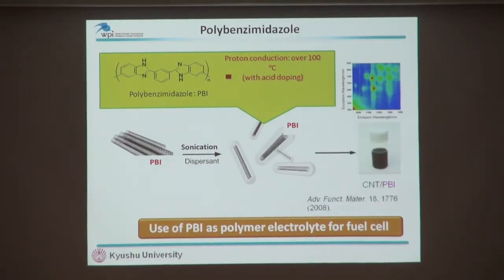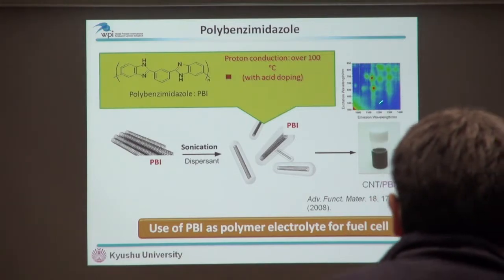And so this is just the beginning. The paper was published a long time ago. We used PBI to stabilize carbon nanotubes, and the result is like this. And when we measured photoluminescence, you can see a spot right here. This is proof that the carbon nanotubes were dissolved with the aid of PBI. So the dissolved carbon nanotube structure is individual, and then we can observe fluorescence from the solution.